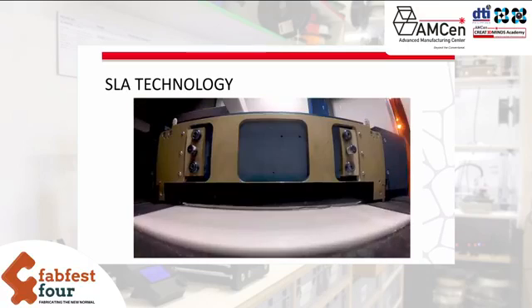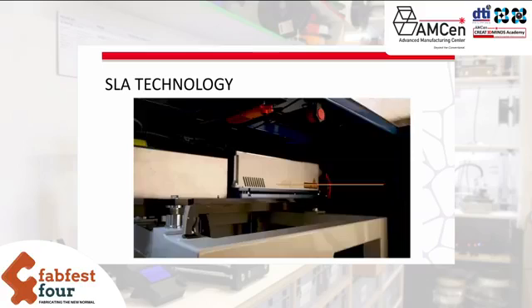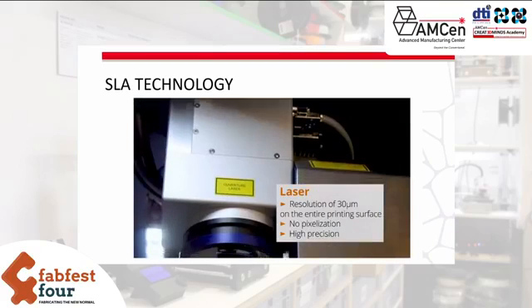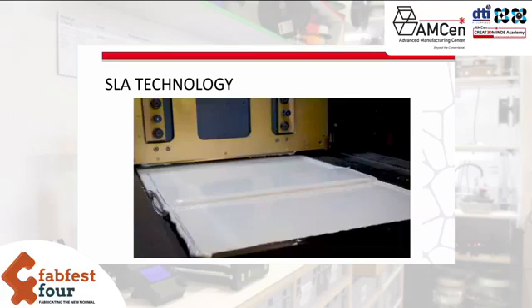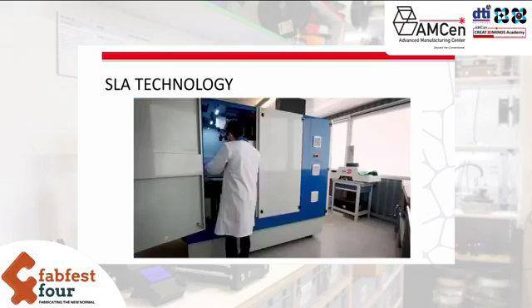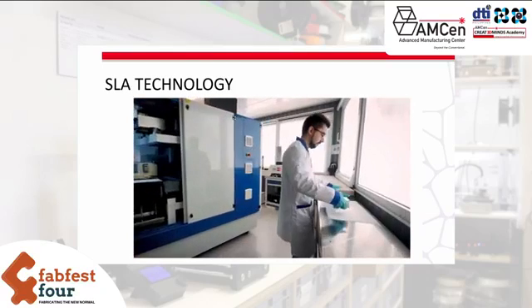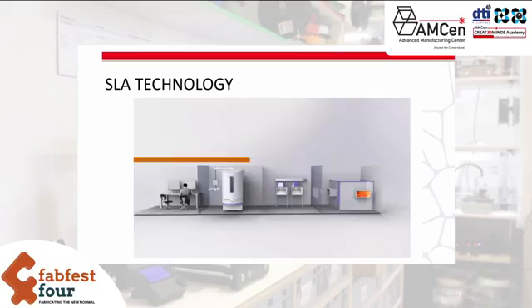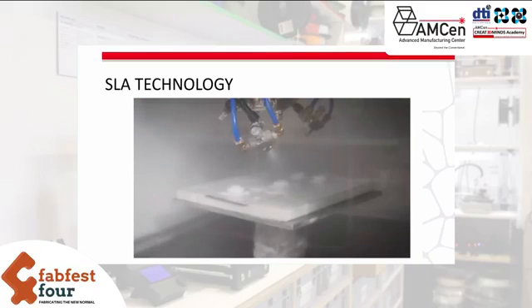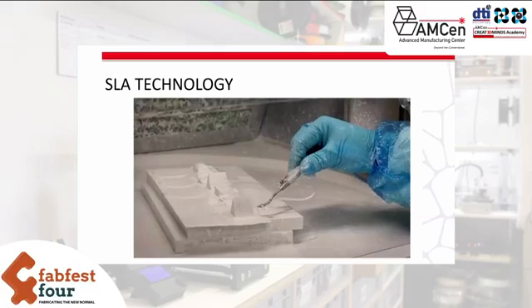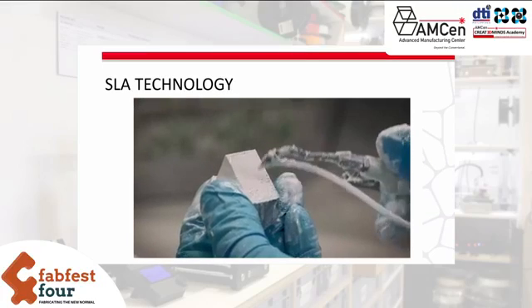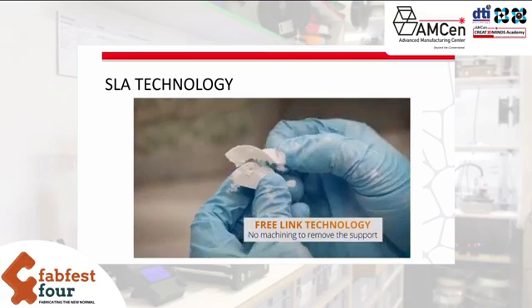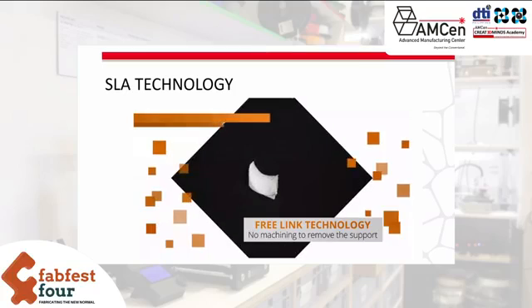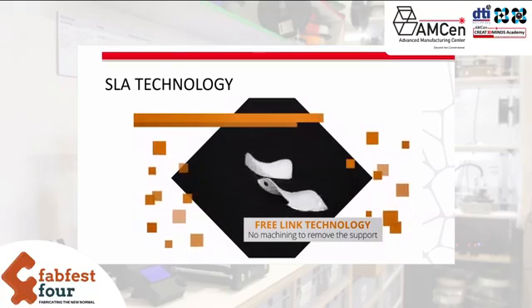And at the beginning of the printing run, the blade spreads a thin layer of slurry on the printing platform, and the UV laser, very accurate, will cure the area to cure, as you can see on the video. After the curing of all the layers, we remove the printing platform from the printer, and we do what we call the cleaning step. We have to blow in order to remove the uncured slurry in contact with the parts. So we blow with a mix of compressed air and a specific solvent to remove the uncured slurry in contact with the part. And as you can see, it is very easy to remove the support from the part. We do not have to cut any links, any pillars, and so on.